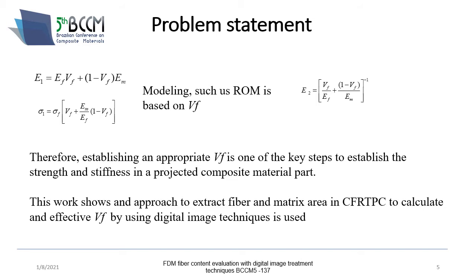One of the advantages of knowing the volumetric fiber fraction is to employ methods such as the rule of mixtures or the inverse rule of mixtures that are based on the volumetric fiber fraction. So this work shows an approach to extract matrix and fiber characteristics in carbon fiber reinforced thermoplastic composite. Calculate the volumetric fraction by using digital image techniques.